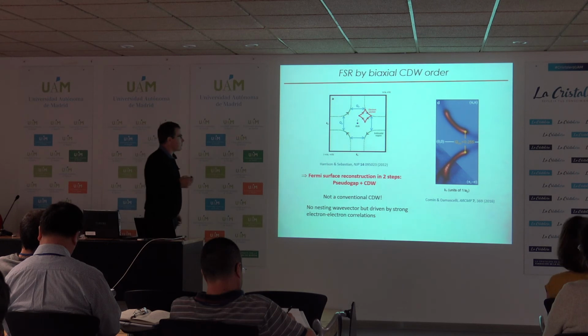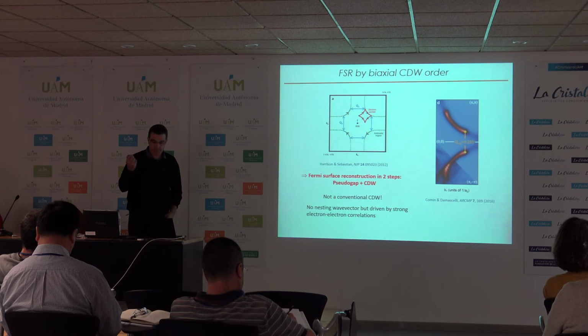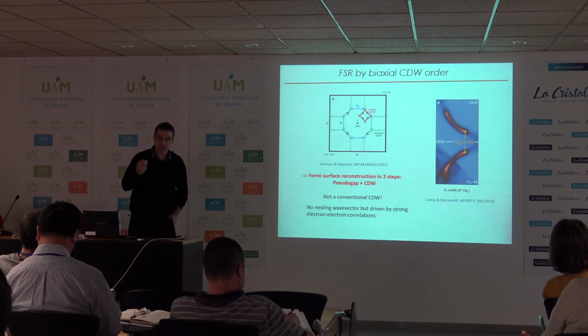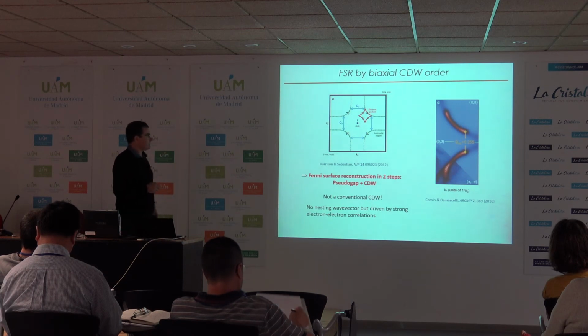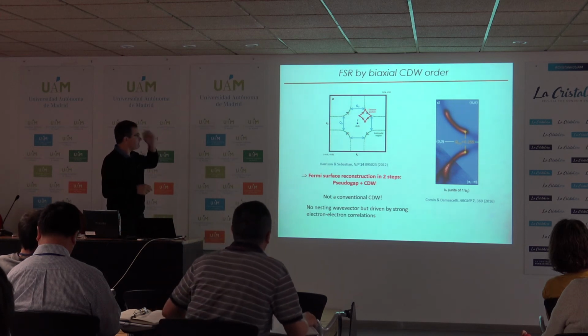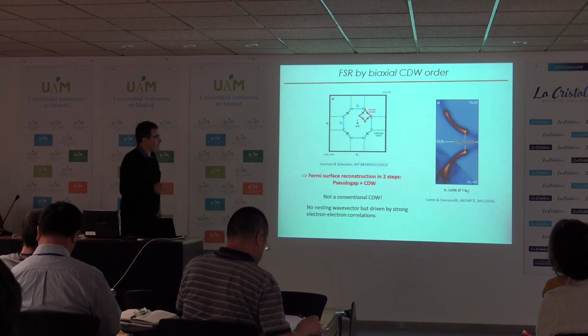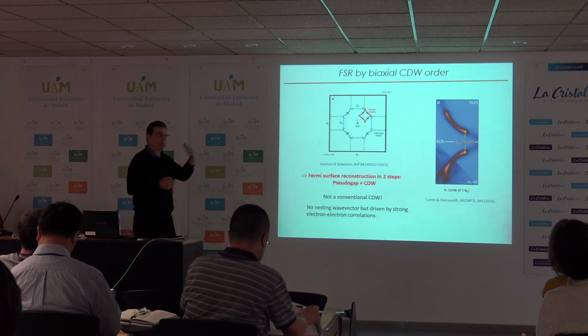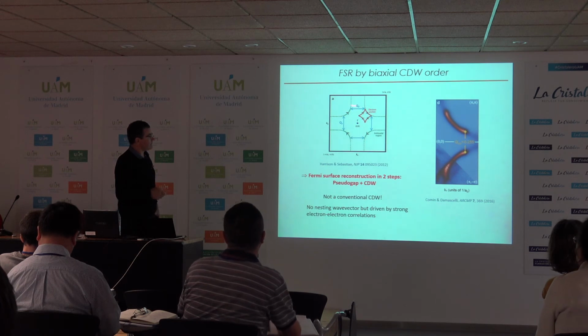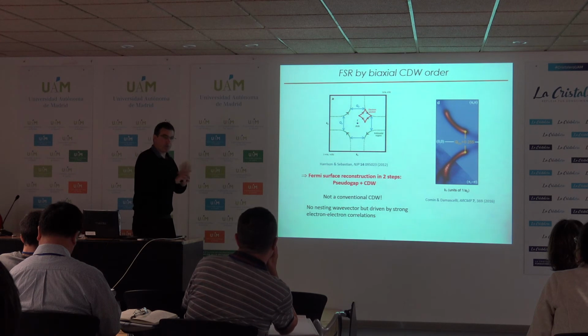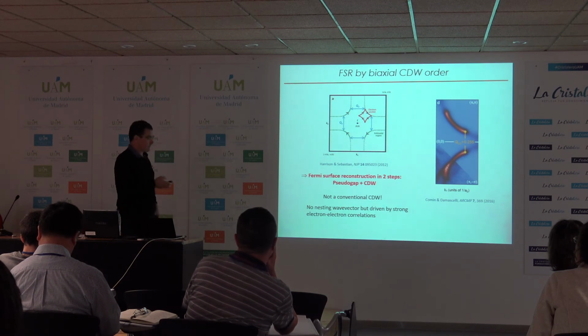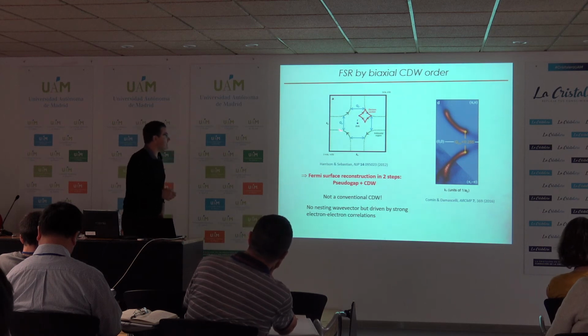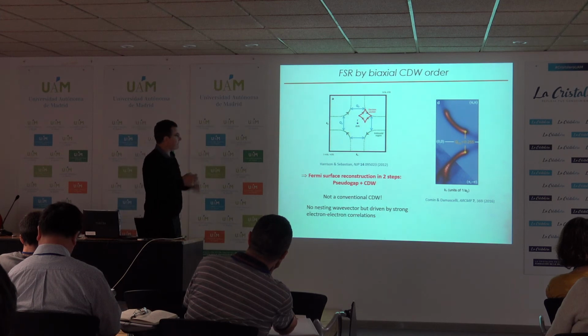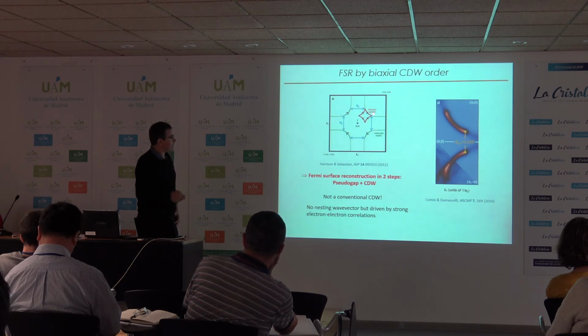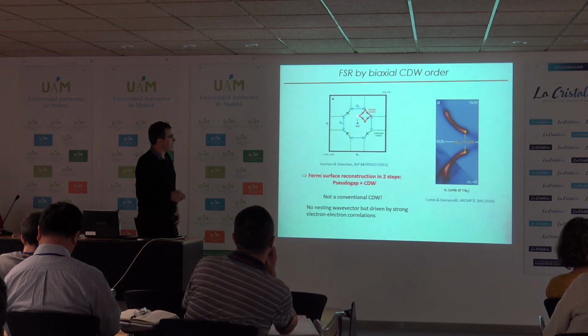And I would say that the current proposal of how to reconcile charge density wave with an electron pocket has been discussed phenomenologically by Neil Harrison and Suchitra Sebastian. Basically, this Fermi surface reconstruction appears in two steps. First, you open a pseudogap at the antinode. Otherwise, if you fold the Fermi surface, you will have too many pockets to explain the density of states measured by specific heat. And from this pseudogap Fermi surface, which has Fermi arcs or small pockets, you fold them with the bidirectional charge density wave vector, along Kx and Ky. So this Fermi arc becomes here a small electron pocket.